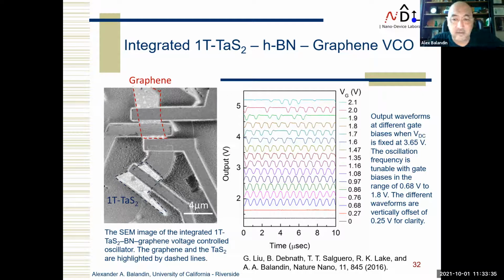And then we made a three-component integrated device, which consists of three different two-dimensional materials, and we are using the specific intrinsic functionality of each material. So we're not trying to use a bandgap in graphene or anything like that. Graphene here is acting as a voltage-controlled resistor, and for that you don't need a bandgap. The way it works, you can see here: this is one tantalum disulfide active device, connected in series to a graphene FET, which is just a voltage-controlled resistor. I can change the resistance of graphene by applying gate bias through a top gate, and the boron nitride layer acts as a cap layer on tantalum disulfide, and as the gate dielectric on the graphene side.